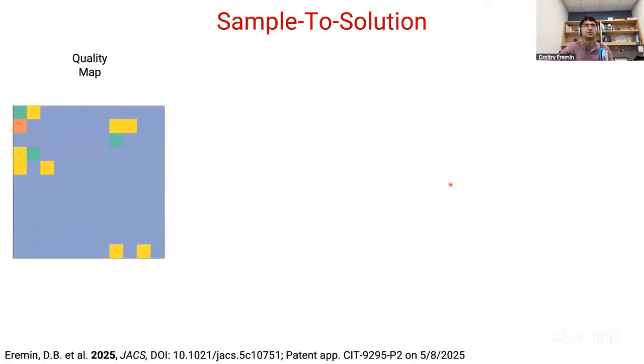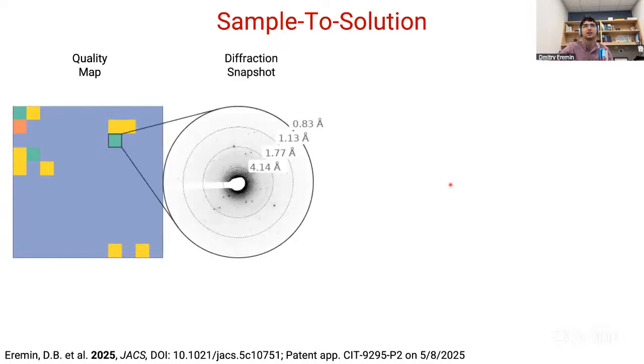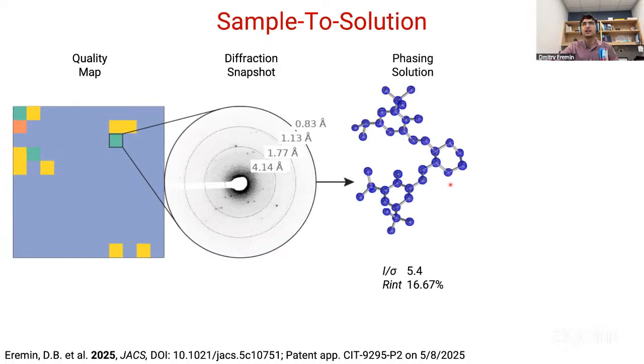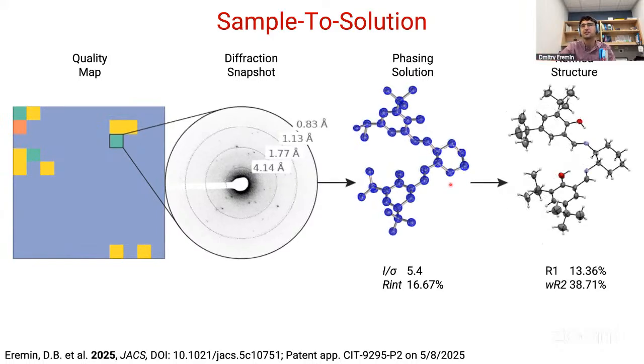So basically, sample to solution, you have this map. Reyes identifies the potential diffraction snapshot where you will go and collect a particular data set. And then you will get, with a package called AutoSolve that we've developed as well, the initial phasing where you can have pretty good statistics. If it correlates with what you think the molecule should look like, you will proceed and get the refinements.